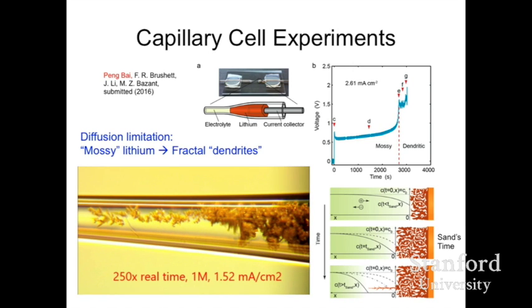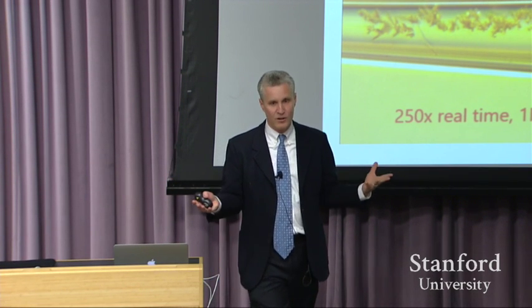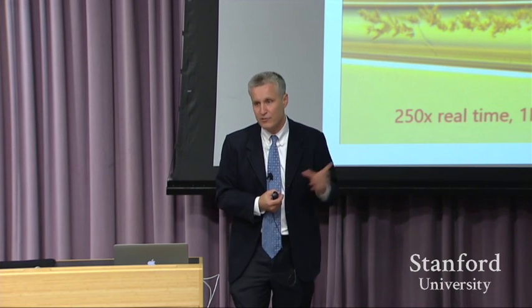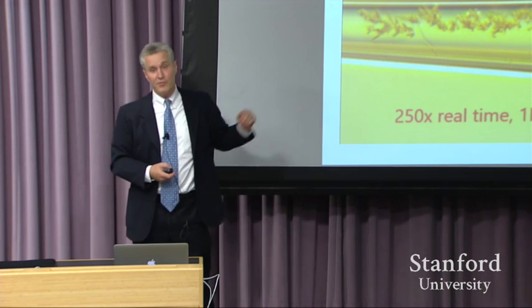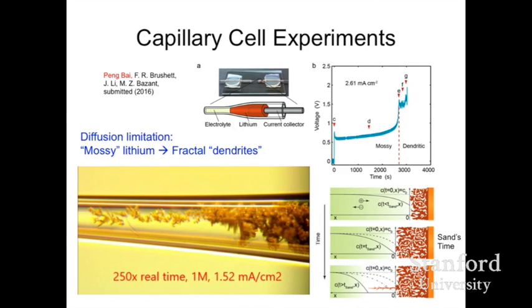Okay? Now, in this field, people use the word dendrite to mean anything which is not flat. And now I'm arguing that that's, again, wrong, because you're, again, missing the mesoscale physics, which is the theme of this talk, that not all non-flat things are the same. Okay, and as you just saw, there are at least 2 different transport mechanisms here, right? So what you saw at the beginning is what's sometimes called mossy lithium, and I'll explain to you in a minute what's actually going on there, and it's something different. But when you do reach transport limitation, what we show quantitatively in this paper, you get this very filamentary and fragmented fractal object, and that's the dendrite. That looks, in fact, very much like what I showed you on the previous slide.